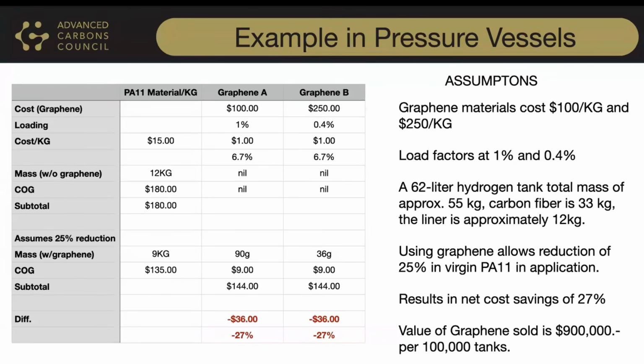So now when we drop down to the bottom half of this table, we assume that because of the improved performance of the graphene, it would allow us to reduce 25% of the virgin material because we're getting a much better performance out of it. And this is based on data that we've actually recently tested. So the mass of the virgin material with the graphene in it now gets reduced to 9 kilograms. So the cost of goods drops to $135. The added cost of graphene in both cases is $9, even though one is priced 2.5 times as much as the other, but because of different load factors, you need less of the second.